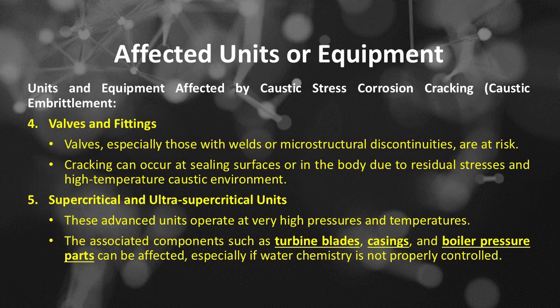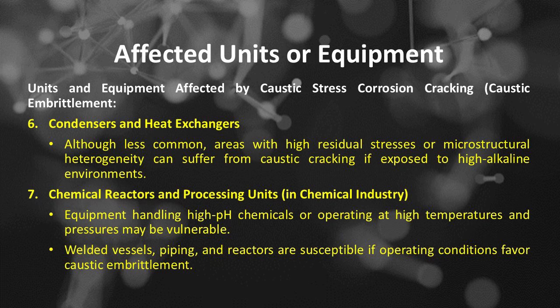Number 5 of units and equipment affected by caustic embrittlement is supercritical and ultra-supercritical units. These advanced units operate at very high pressures and temperatures. The associated components, such as turbine blades, casings, and boiler pressure parts, can be affected, especially if water chemistry is not properly controlled. Number 6 is condensers and heat exchangers. Although less common, areas with high residual stresses or microstructural heterogeneity can suffer from caustic cracking if exposed to highly alkaline environments.